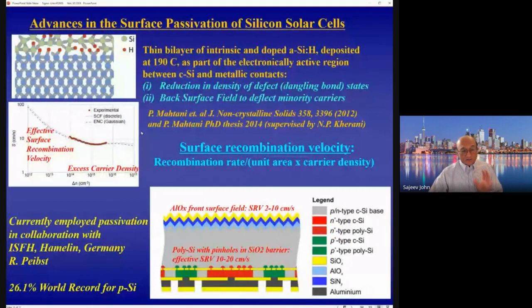So the other extremely important feature of silicon solar cells, or any solar cell, is recombination processes that can occur at the surface of the structure. The surface of a structure can have defects, for example, dangling bonds, which are not bonded to any other silicon. Those create defects within the band gap and trapping centers for electrons and holes, where very rapid recombination can take place and most of the energy can be lost. And a lot of effort in photovoltaics has been focused on trying to create surface passivation techniques for reducing this surface recombination.